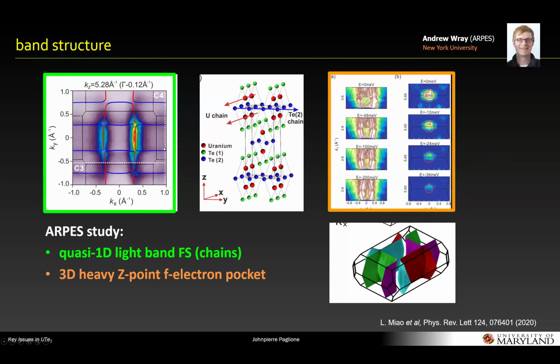Okay, so another hot topic is the band structure, and for obvious reasons, we need to understand how the electrons are situated in this material. And from early on, there's been a bit of discrepancy in the ARPES data. I'm a big fan of Andrew Wray, and I trust his work far above some other groups, but nevertheless, it was really nice to see that the early ARPES data showed some semblance of the calculated band structure, in particular showing these quasi 1D sheets that are shown by the red and blue lines here, the calculation.